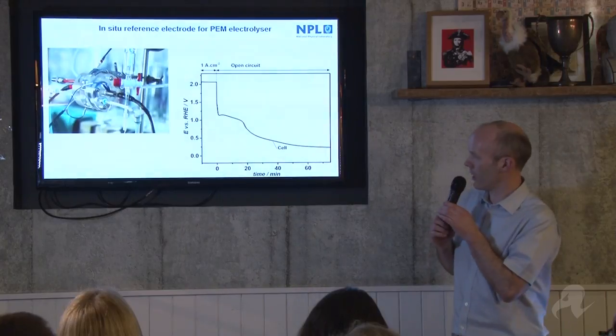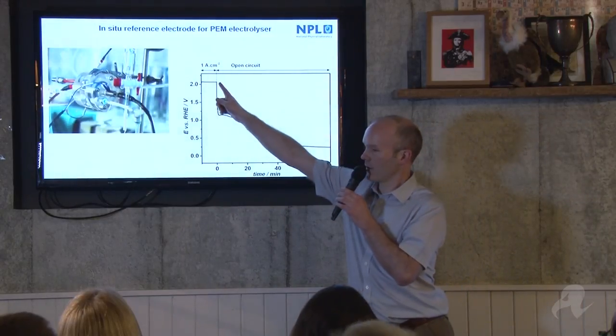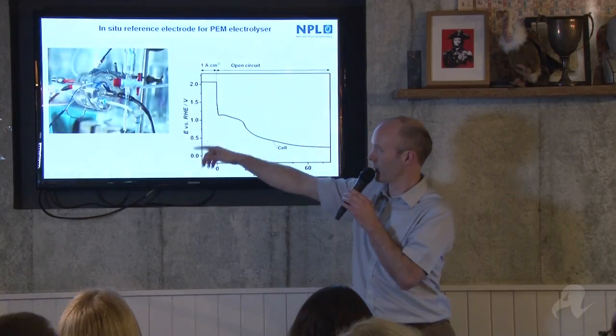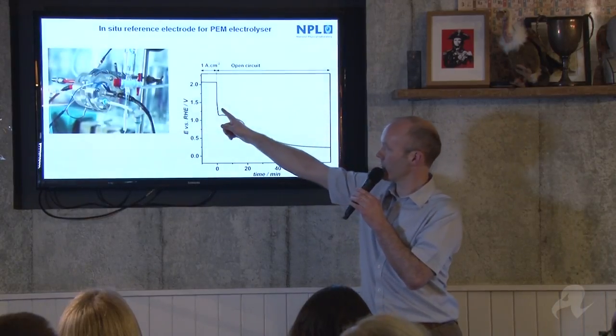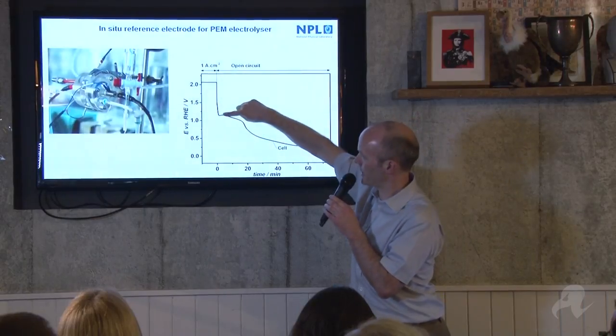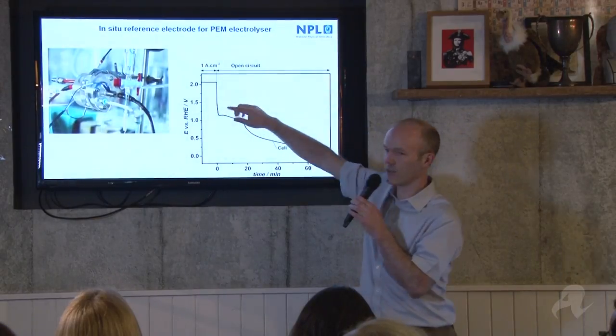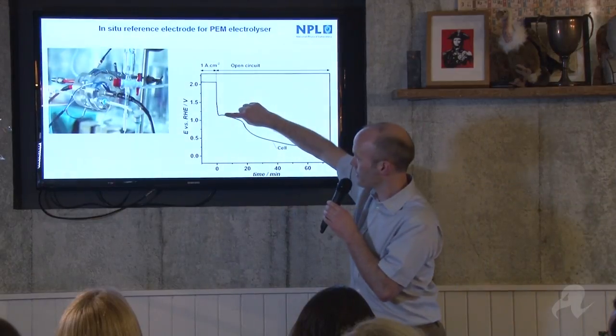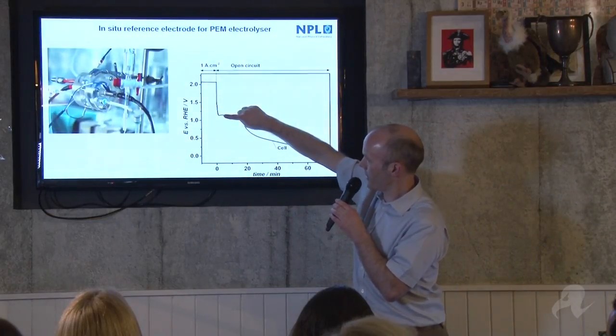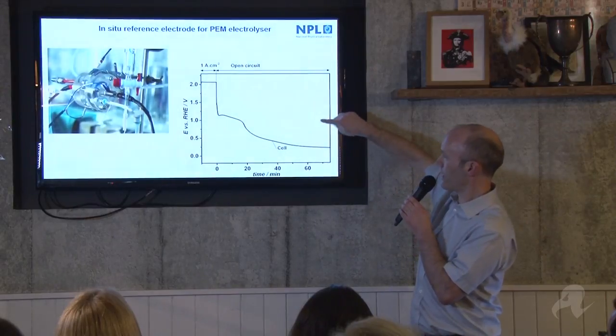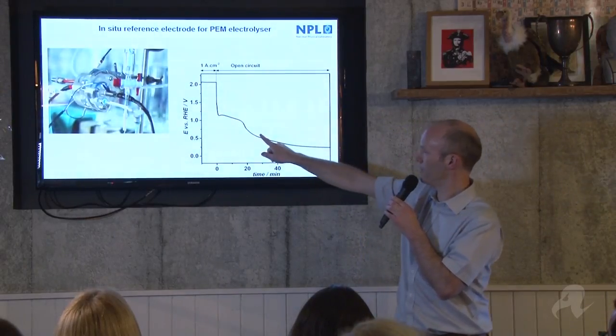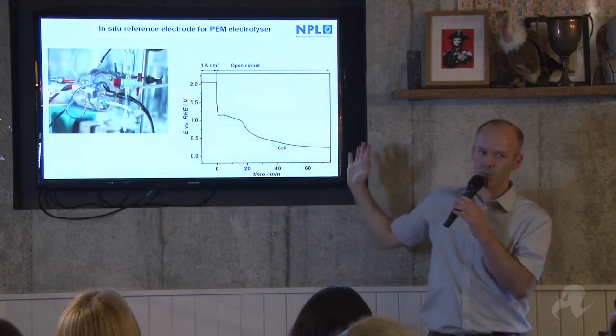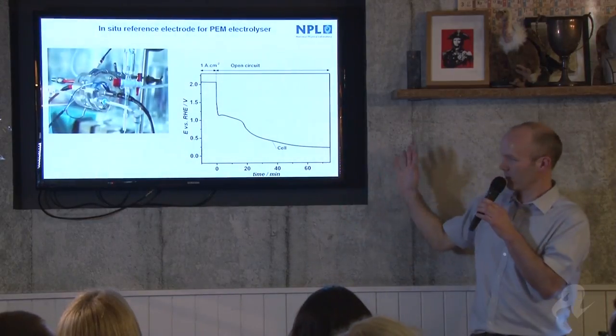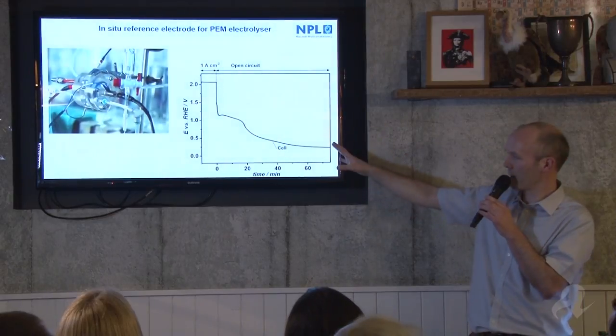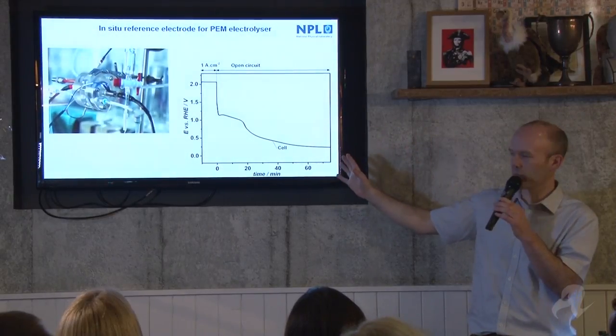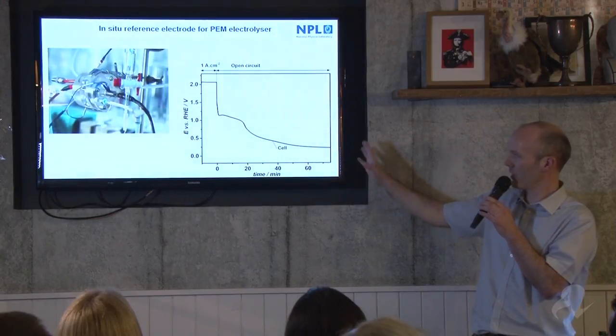So when you switch off an electrolyzer, people were seeing this even in the commercial refueling stations. The open circuit potential, this is the drop that you immediately get due to the ohmic drop. So as you switch off the current, the potential drops. And then you would expect the potential just to sit here. But what they saw in practice was the potential dropped with time. And when that's happening, you know something isn't right. So there's some chemical reaction happening there, and it was leading to degradation of performance of these refueling stations. And nobody could explain what it was.